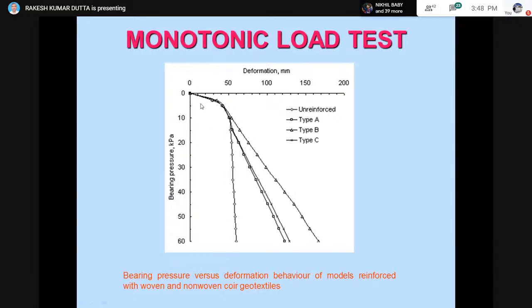But if you put a geotextile, type A, type B, type C, you will find that though there is no increase in the bearing pressure up to a certain level, beyond a certain deformation there is a sudden increase in the bearing pressure values. The bearing pressure is going up and up continuously. So this indicates that these kinds of materials can be very good where rut depth is going to be a major problem. Rut depth is basically when wheels and bullock carts move over the kacha road, they cause a deep depression on the road surface.